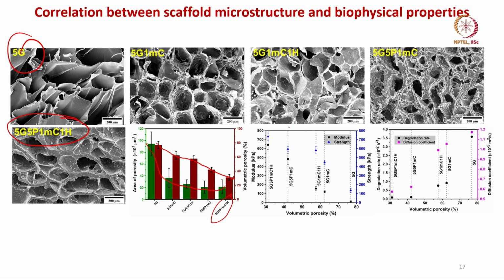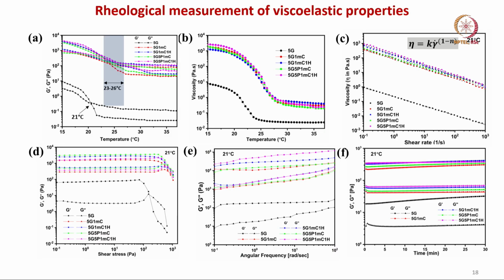If you look at this strength property, it shows this kind of trend. If you look at the elastic modulus properties, it shows almost this kind of trend, that it is very close to 0 when volumetric porosity is very high, right. So, 3D porous architecture qualitative and quantitative evaluation was very important, because that allows you to correlate the microstructure with the compressive strength, modulus and diffusion degradation rate, and these effects of cross linking density and inorganic nanofiller are strongly reflected in the scaffold morphology.